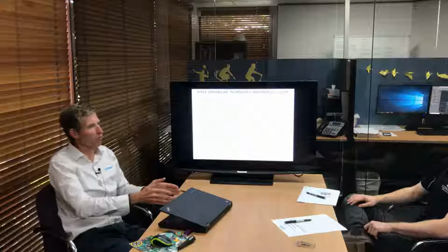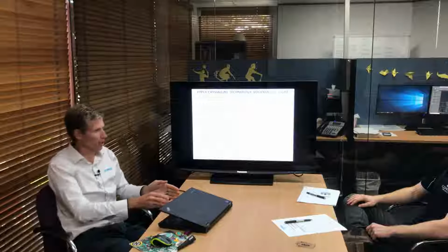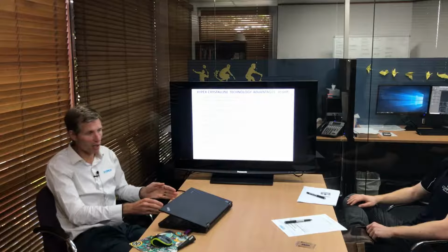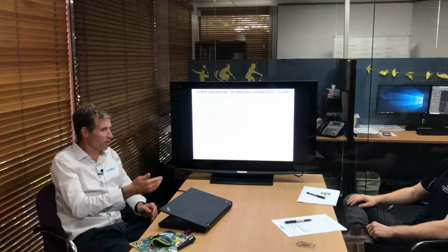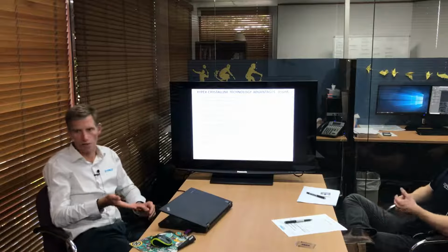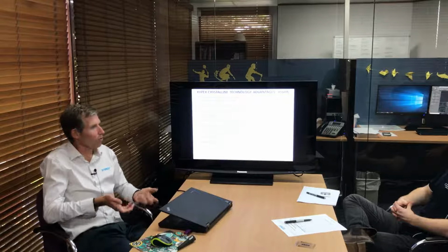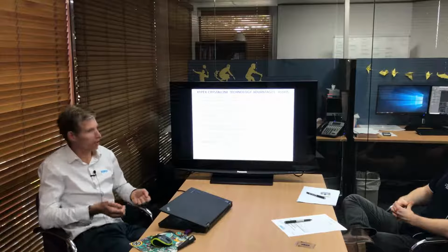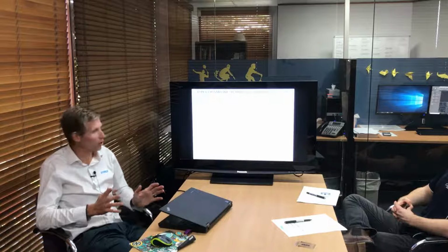Now, one of the issues you tend to find with these barrier products, or for example surface coatings and membranes, is there needs to be an awful lot of attention to detail put into surface preparation to make sure you get consistent adhesion and don't have any delamination issues. One of the main reasons for failures in a lot of surface applied products is because they haven't managed to get all the oils, laitance and curing compounds, etc., out of the concrete prior to application. And as I say, if you put a widespread membrane on something and get a small pinprick and a bubble somewhere, before you know it, you really don't know where the potential problem could be on some of those structures.